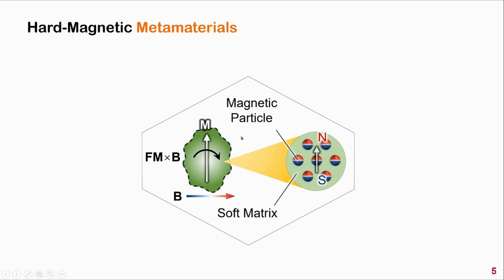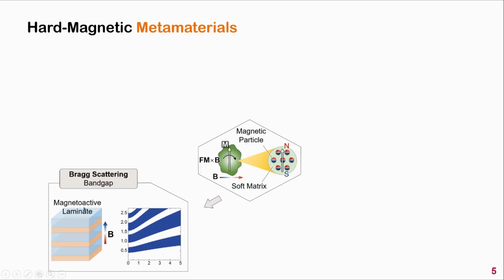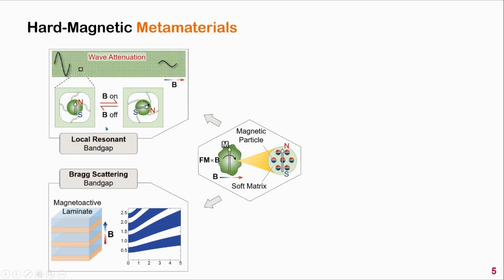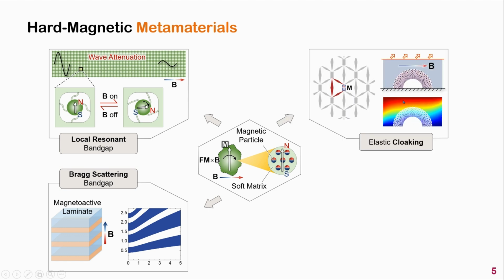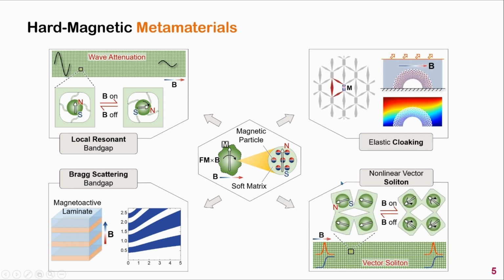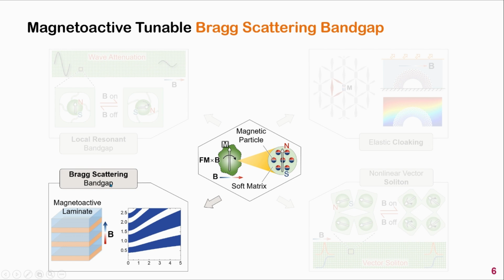Here, my research interest is to integrate the unique transformative ability of hard magnetic materials into metamaterial design to achieve novel soft magnetoactive metamaterials for tunable wave manipulations. This includes the tunability of Bragg scattering bandgap, local resonant bandgap, elastic cloaking, as well as the tunability of nonlinear waves, the soliton. Okay, first let's see the tunability of Bragg scattering bandgap in the magnetoactive laminate system.